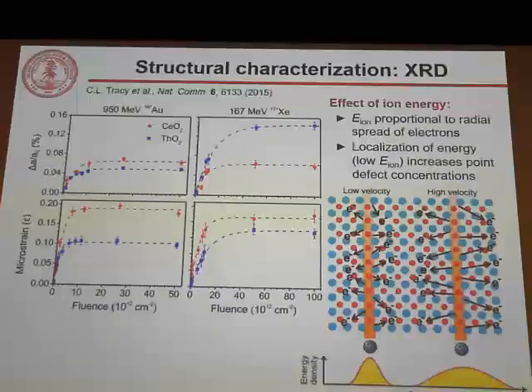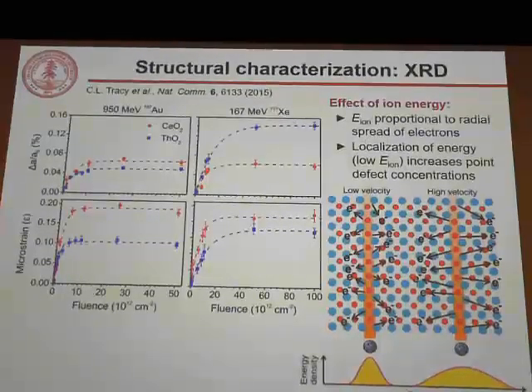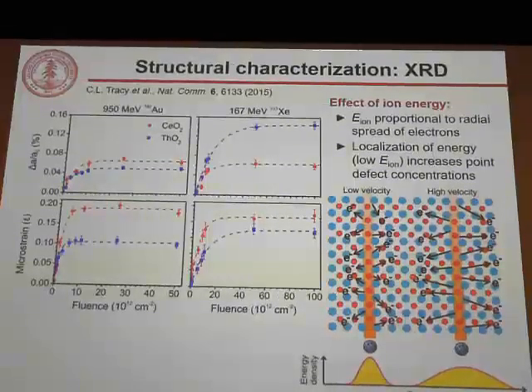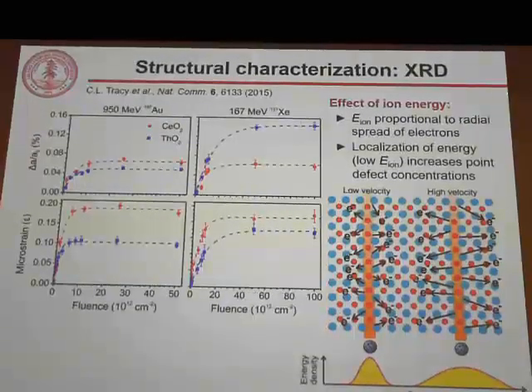What this means is that, kind of counterintuitively, when we reduce the energy, we make more localized energy deposition, so we tend to end up with greater damage due to higher point defect concentrations induced. That's exactly what we see for thorium dioxide. When we move from 950 MeV to 167 MeV, the blue line, the damage induced, increases dramatically. For cerium, that does not occur.